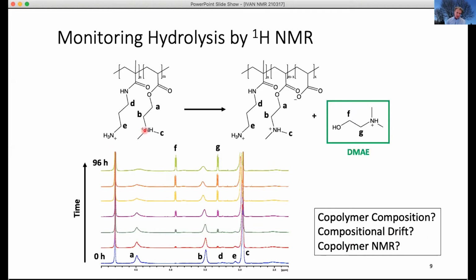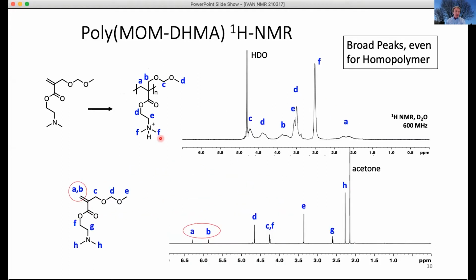So copolymer NMR is a classic way of doing that, but the peaks are very broad. Here is one of our cationic charge-shifting monomers. It's a relatively simple molecule, but in the polymer you get broad peaks. And if you were to make a copolymer incorporating another primary amine for cross-linking, it might be difficult to see the shedding of the small functional group or the composition of the copolymer.